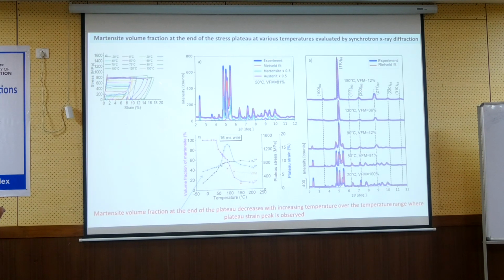At 100, where the long plateau is, we have at the end of the plateau half of the microstructure in austenite, half. So it's a kind of different. So the question is, why do we have austenite at the end of the long plateau? Because intuitively, the more martensite, the longer is the plateau. But no, we have less martensite and a longer plateau. And we have these deformation bands in the microstructure. So we had to explain this.